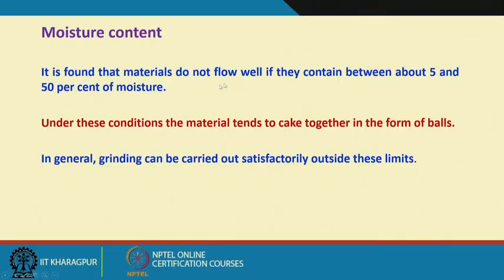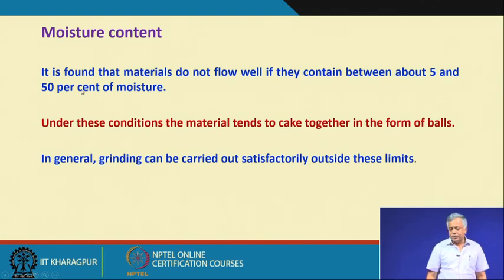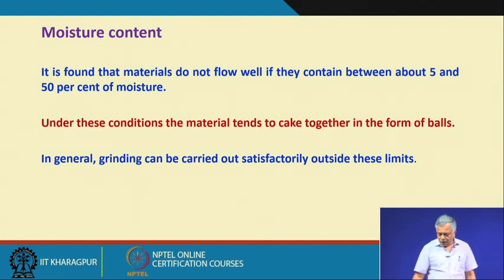In general, when we go for fine particle breakage — that is grinding — it should be done either in dry condition, that is below 5 percent moisture, or in wet condition with more than 50 percent moisture; otherwise we have problems.